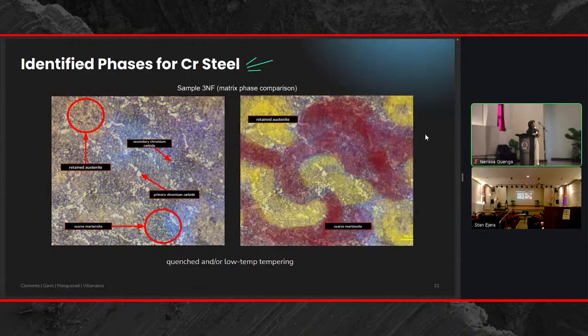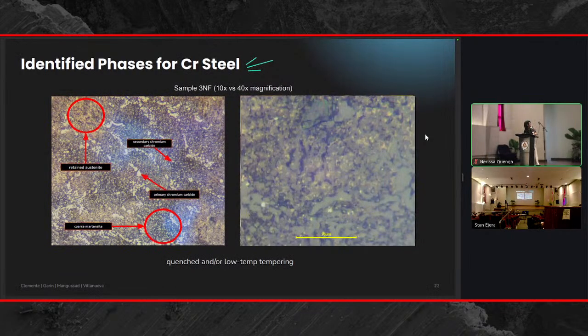Here as well, we have the identified phases for chromium steel. Chromium in AISI D2 has a tendency to form carbides as it's quenched and tempered. Here we see those primary and secondary carbides. In the matrix, we have retained austenite and some formation of coarse martensite. According to literature, this is typical of quenched and or low temperature tempered samples.